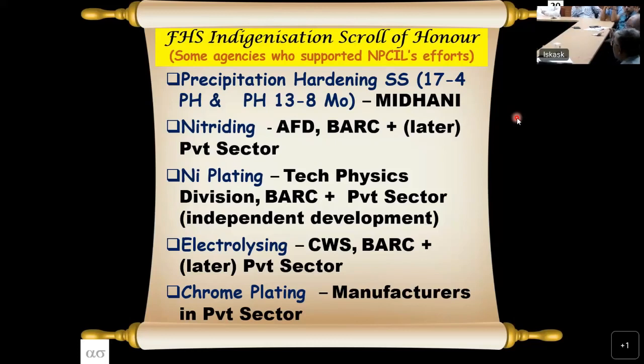In gas nitriding, you take 17-4 PH and then apply ammonia to that, and nitrogen goes in. The problem with that is that a chromium oxide layer is there in the stainless steel. So first of all, you have to break the chromium oxide layer, and only then will the nitrogen penetrate. This was done by AFD. Without AFD, we could not have done this. The only thing was, this is a high temperature operation, some temperature lower than, let's say, 500 degrees centigrade. It could not have been done in normal furnaces because you are dealing with ammonia.